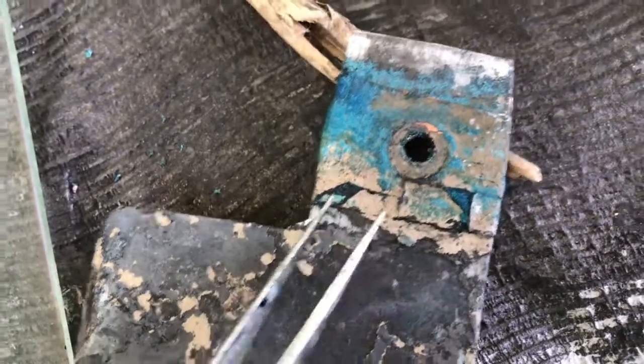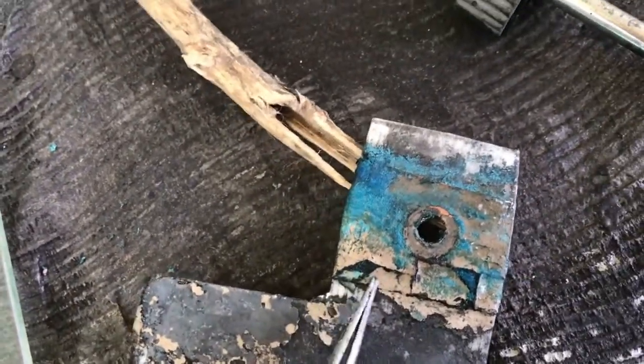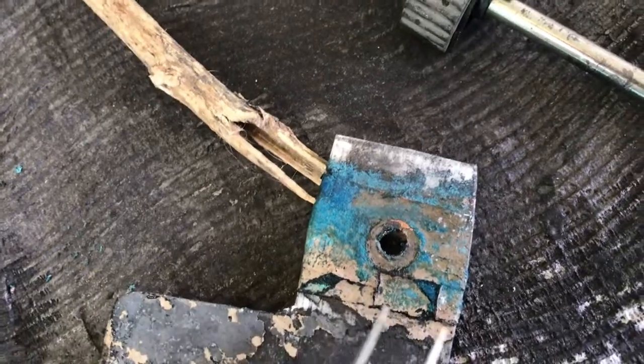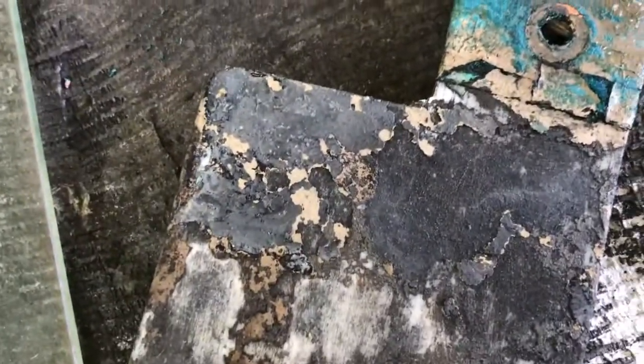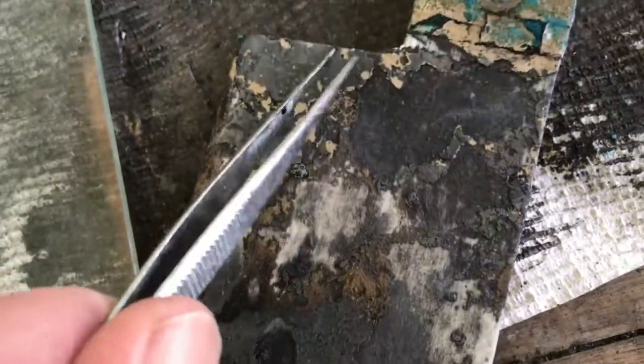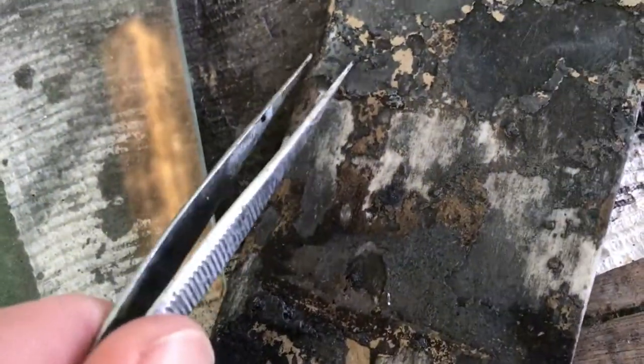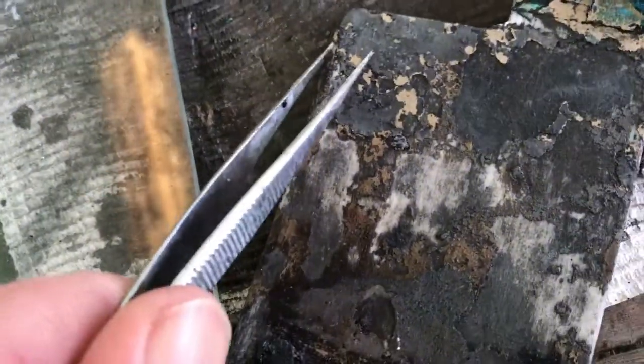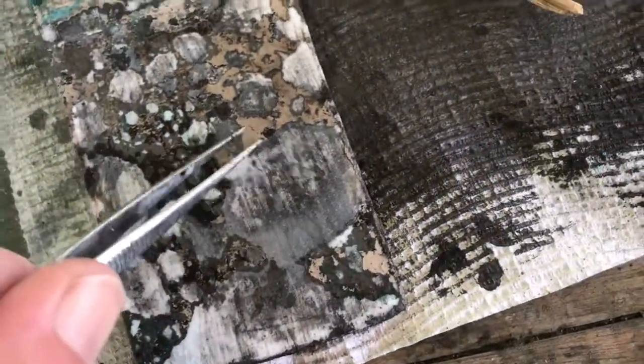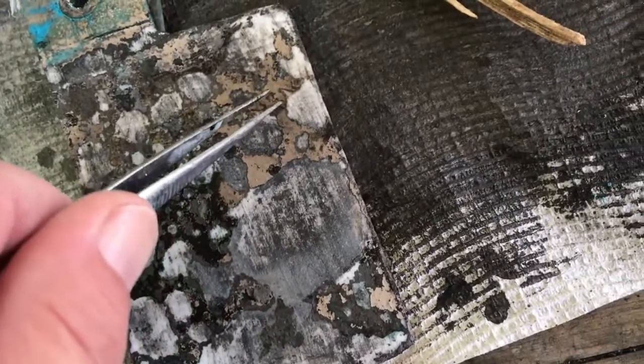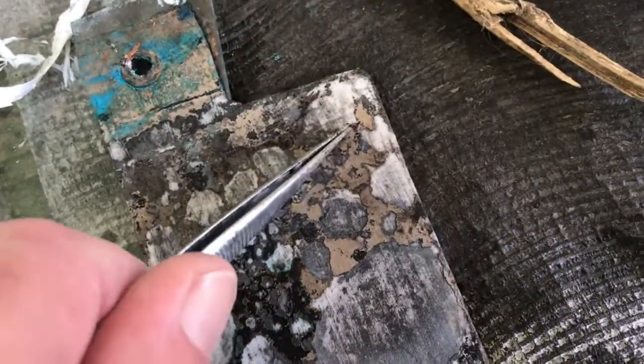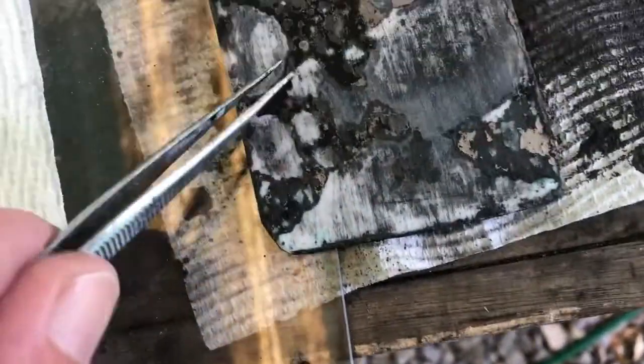So this is the edges. It's just sort of stuck in there, but the plating failed, or it's due to the charge. The negative sides aren't like this, from what I know of. The potassium hydroxide shouldn't be etching into the nickel. Maybe the nickel plating wasn't thick in areas and allowed the electrolyte to get in and under, perhaps around the edges, or any other defect I had in the area.